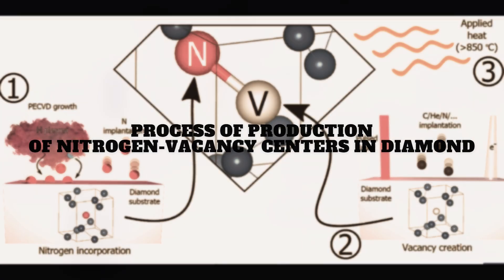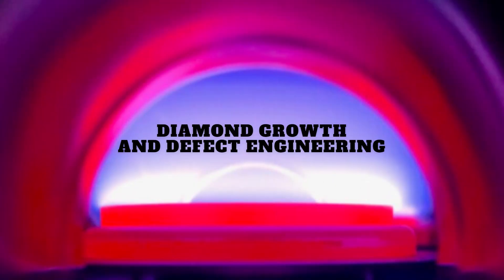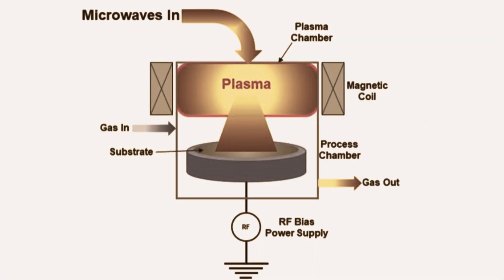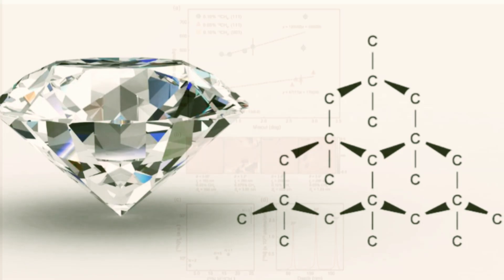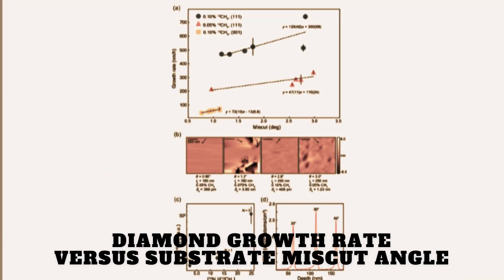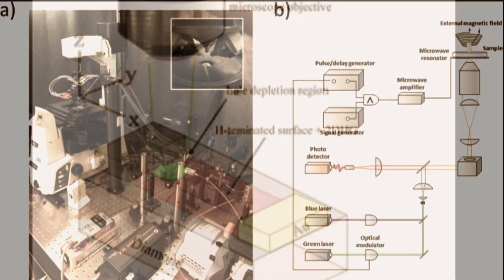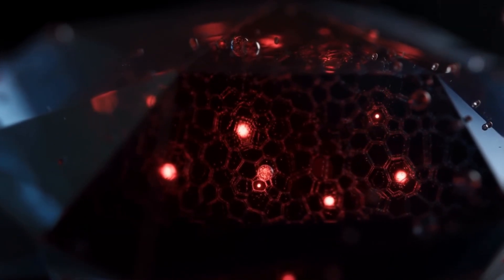Creating these ensembles is no simple task. The crystal orientation of the diamond is crucial. Jayak's team grows diamonds on the 1-1-1 plane, which naturally aligns NV centers in a favorable way. They also use plasma-enhanced chemical vapor deposition, PECVD, to carefully control the number, position, and depth of NV centers. This allows them to confine the NV centers to a thin layer just nanometers below the diamond surface, close enough to detect external signals but protected enough to preserve their delicate quantum properties. The team must incorporate NV centers within nanometers of each other and of the surface, balancing proximity for sensitivity with protection for stability.